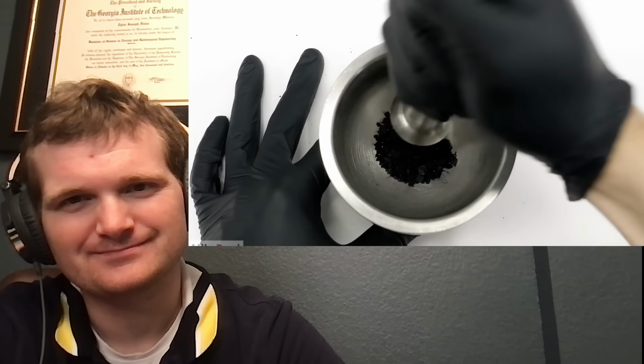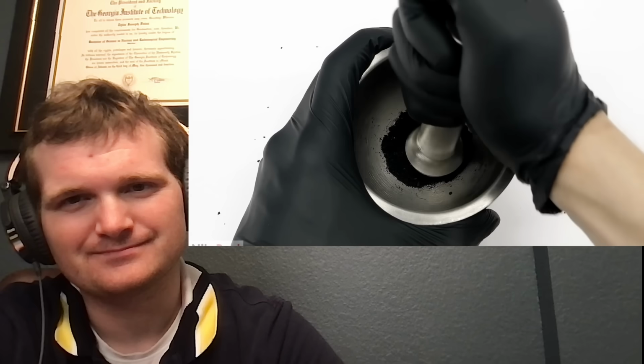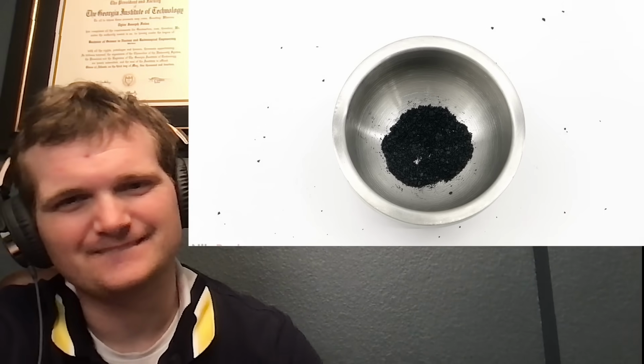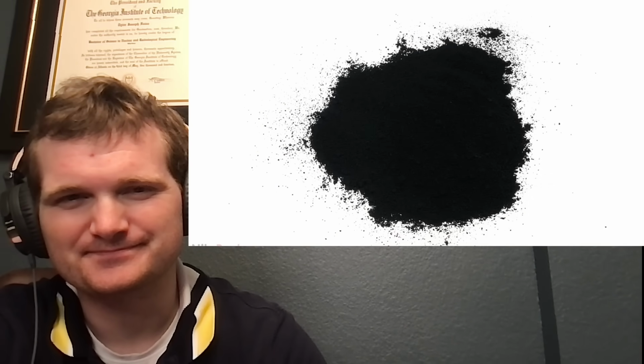To do this, I had to turn all my beautiful pellets back into a powder, and I started by just trying to crush them by hand. It worked okay to break it up into small bits, but these bits were way too hard, and I wasn't able to crush them into a powder. So instead, I threw them all into a small blender. Then after that, I screwed the top on, and I ran it for several minutes. Blending superconductors. Who knew? This gave me a relatively fine powder, which I loaded back into the furnace.